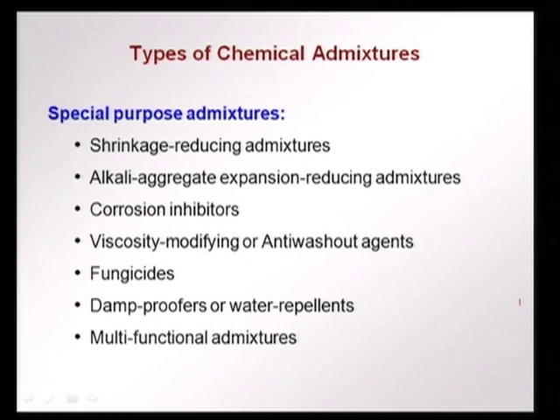There are also several other special purpose admixtures like shrinkage reducing admixtures, which are glycol based. They reduce the surface tension of the pore water, and therefore, there are less capillary stresses when water is released by evaporation or by hydration. There are admixtures which reduce the alkali aggregate expansion. There are corrosion inhibitors which prevent corrosion from occurring very easily. They increase either the chloride threshold or prevent the corrosion process from happening, they cut the electrochemical process.